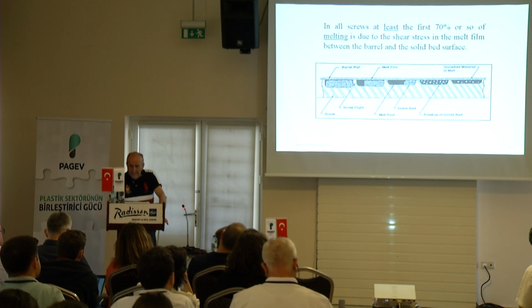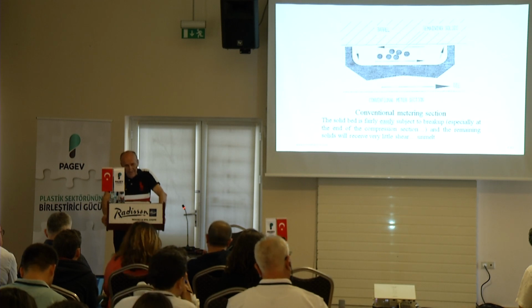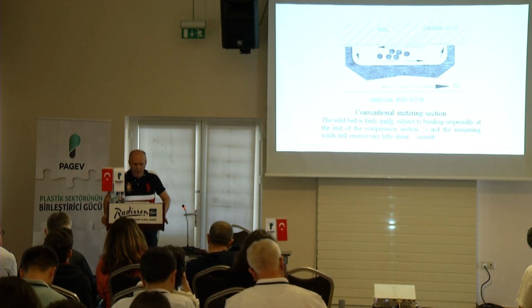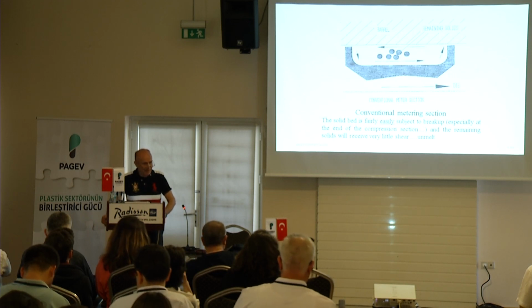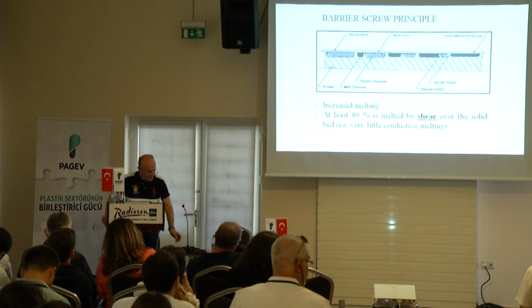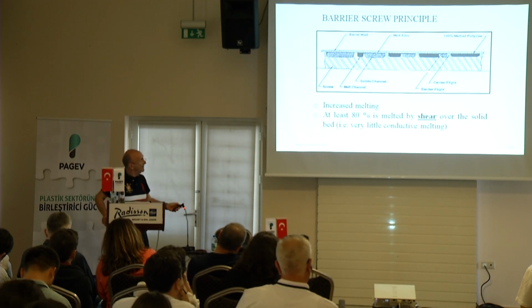This is the screw without a barrier. What I pointed out already is that if in the channel I have unmelted pellets or chunks of material that have not been melted, they just float, or I may say swim, in the melt. They are not likely to get melted. So it is better to squeeze them, to force them against the barrel. And this is the birth of the barrier screw.